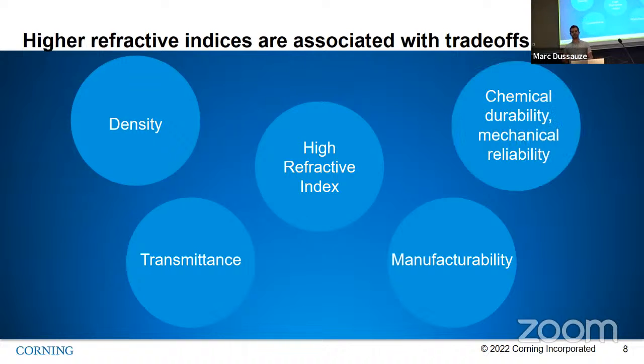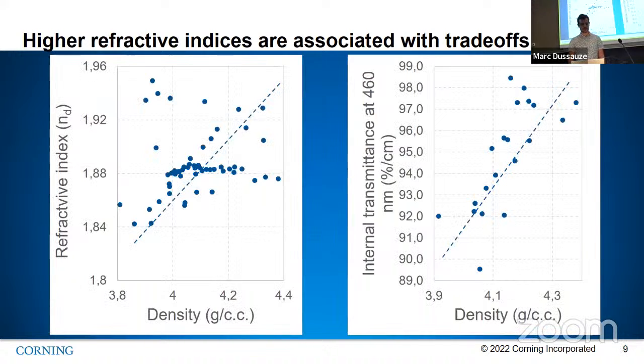Obviously, there are all kinds of other properties we have to look at, also chemical durability, because those pieces of glass are going to be used as wafers, so they're going to go through different cleaning steps in the industry that will create those AR headsets. We have some mechanical properties to meet as well. So it's a whole set of properties that we need to keep in mind. And obviously, a lot of them are kind of contradictory. For instance, usually when we try to boost transmittance by using specific elements, we decrease the manufacturability because the glasses are going to be less and less stable. Same thing if we want to decrease density, usually we decrease transmittance as well. So it's very difficult for us to find the right balance, and that's basically the work we've been doing.